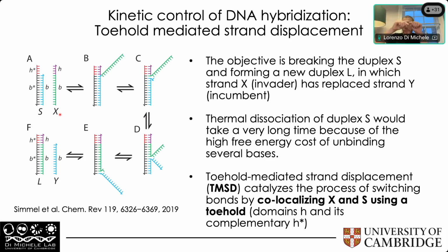Okay? So if you switch one nucleotide at a time, you basically don't have to go over this massive free energy barrier. You can go around it. So again, you can think of this as having to climb a free energy mountain for this switch between bonds to happen. But I have a simple trick, which is if I switch one nucleotide at a time, then I don't have to go on top. I just go around in my hypothetical free energy landscape. And this is what can then catalyze this reaction effectively and make it much, much faster.